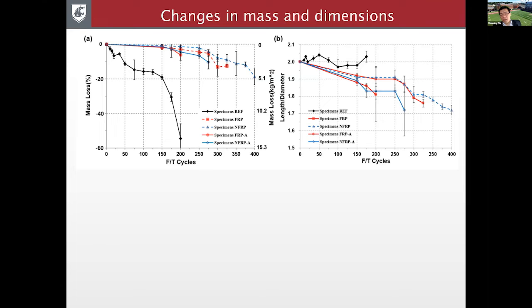Now, it's interesting because the FRP fabric wrapped around the concrete cylinders, and at each end we have about 5 centimeter or 2-inch additional protection, but overall the top and the bottom were not protected by FRP. So over time, you're seeing this change in length to diameter ratio. Of course, for the reference one, the black dots without any FRP, that change is minimum because their deterioration or scaling is somewhat uniform on all sides. But for the FRP ones, because you're mostly seeing scaling on the top and the bottom, you're seeing the length to diameter ratio keep changing.